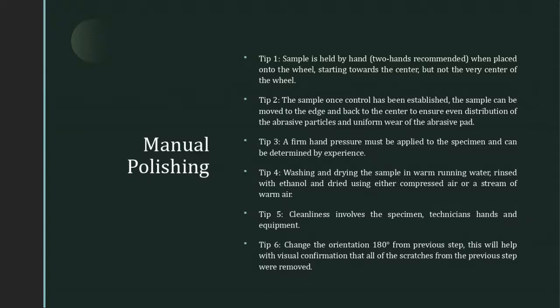Once control has been established, you can move the sample after staying in your spot for 5-10 seconds. Now you can move to the outer edge and back to the center. By doing that, you ensure even distribution of the abrasive particles on the pad, or even distribution of particles on your sample, and uniform wear of the pad, because you're utilizing the full 8-inch pad. If you had a 12-inch pad, same thing—you're going to utilize the whole pad.